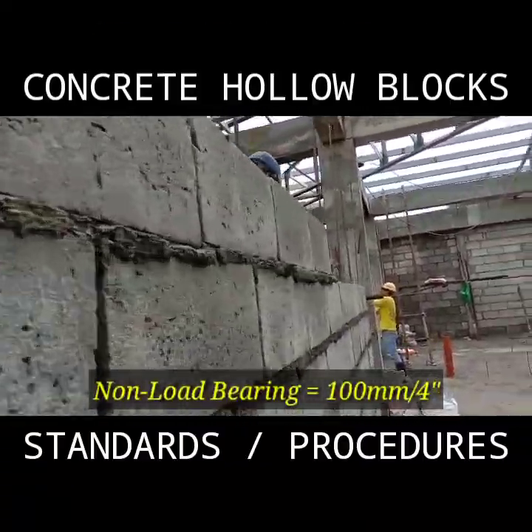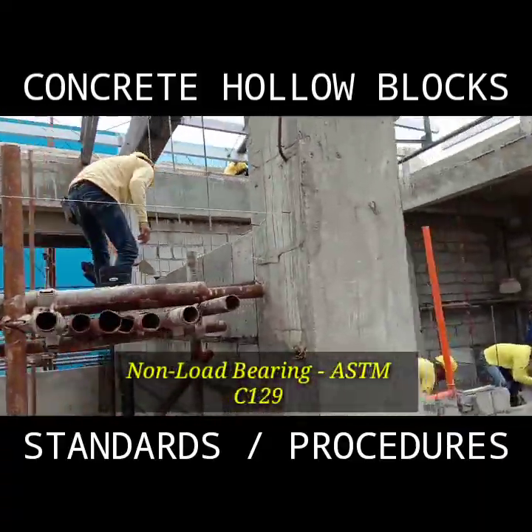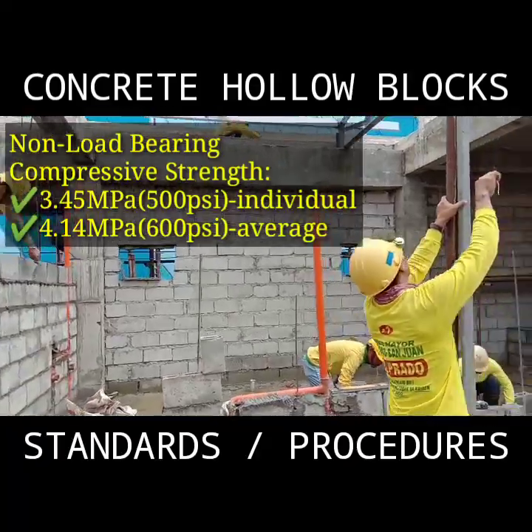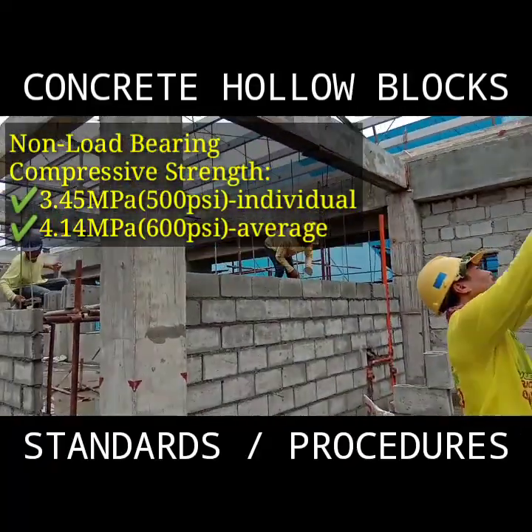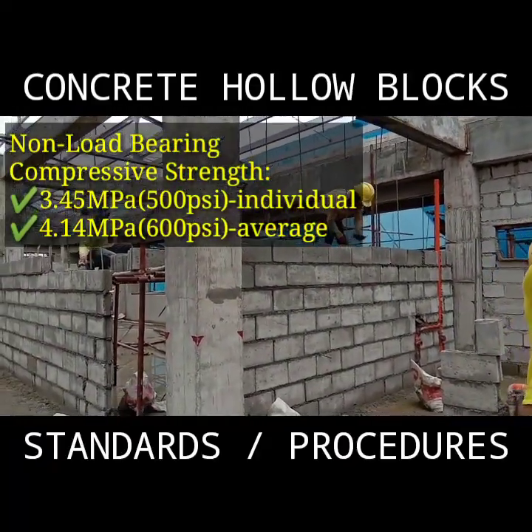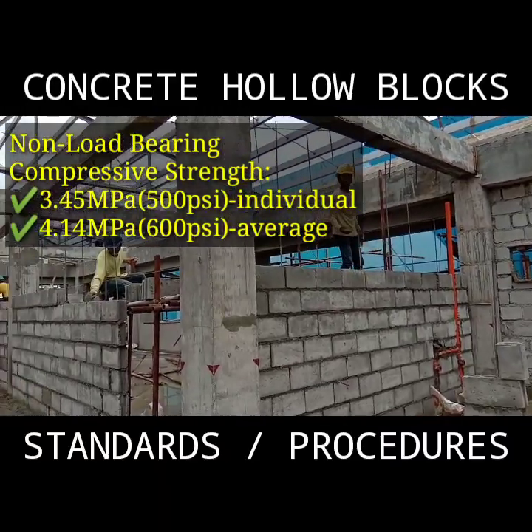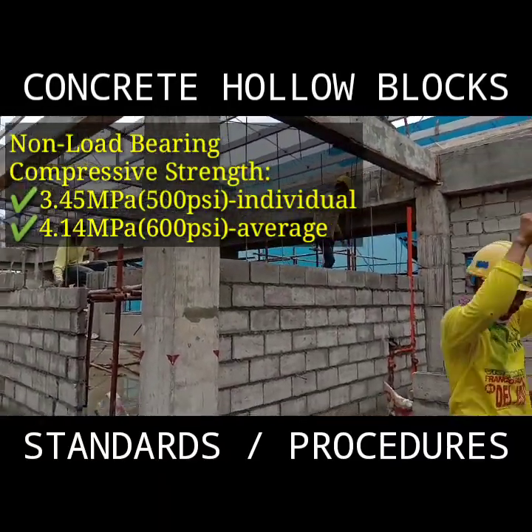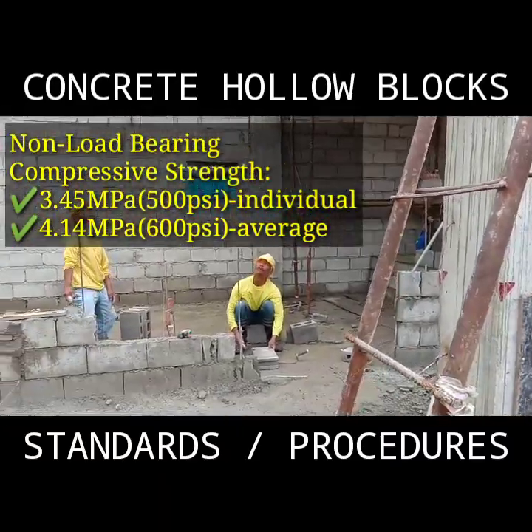However, non-load-bearing blocks are usually 100 mm thick or 4 inches as per ASTM C129 and have an individual compressive strength of at least 500 psi or 3.45 MPa, and 4.14 MPa or 600 psi for its average compressive strength.